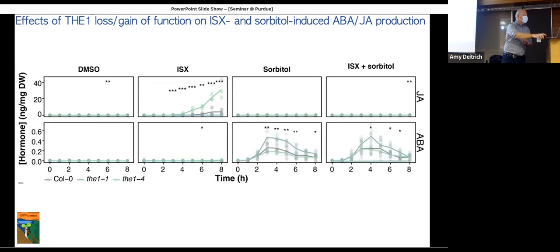And then we got a bit of a surprise. Same experimental setup, but we were measuring ABA. As expected, nothing happening with DMSO and isoxaben. However, when you look at the sorbitol data, you can see that in the wild type you have a nice transient induction. I think this is also a good sign that our mild hyperosmotic stress is not killing the plants, if they go back down. But interestingly, with the THE1 loss of function allele, you get enhanced production of ABA. For the THE1-4, it's not as clear, but it seems to be slightly reduced. And the same situation in double-treated seedlings: you still have enhancement in THE1-1 and possibly a little bit in THE1-4.